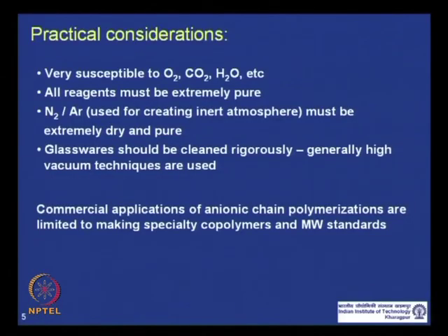As you can now recognize, it is not a very simple reaction to carry out on a large scale, in industrial scales, where maintaining all this purity and these reaction conditions is very difficult, and these reactions are typically done at sub-ambient temperature. So, as we expect, commercial applications of anionic chain polymerizations are limited, and they are not used for making many polymers.